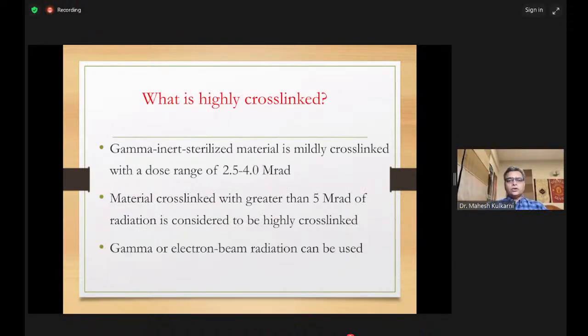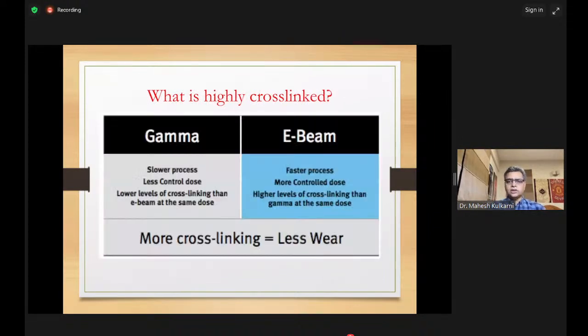So what is highly cross-linked? If you have a gamma inert sterilized material, it is mildly cross-linked if it is subjected to 2.5 to 4 megarad of irradiation. About 5 megarad of irradiation is considered highly cross-linked polythene. So any polythene which is above 5 megarads is probably considered highly cross-linked. What can be used? You can use either gamma irradiation or electron beam irradiation on the polythene itself, which will give you better cross-linking.